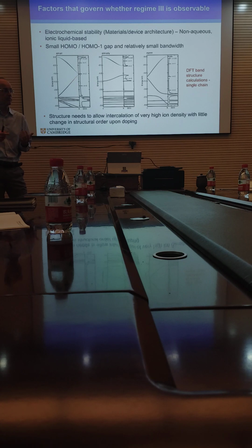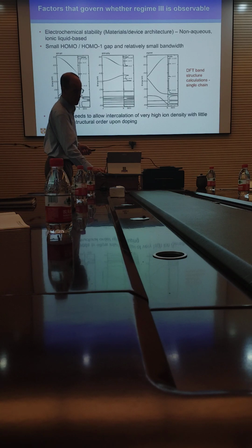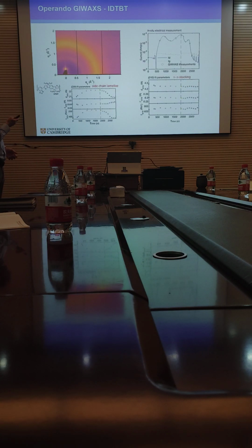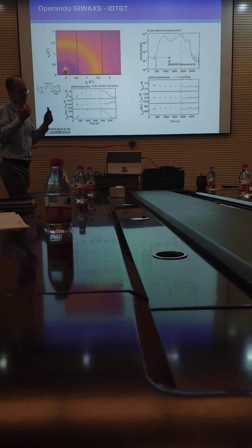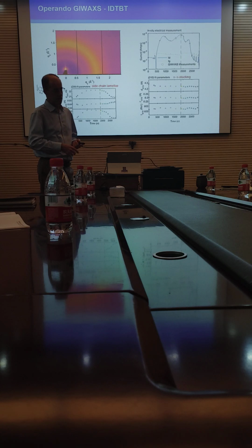IDTBT is quite a disordered polymer, and it's easy and possible to put more than one charge per repeat unit in here. You can see that here, this is an operando GIWAXS measurement where we actually charge and discharge the polymer and take the GIWAXS pattern. If you look carefully, you can see some variations in the GIWAXS pattern as we charge and discharge, but it's not changing very much. It's quite a disordered polymer, so you cannot see very sharp diffractions. But as you push these ions in and take them out again, the microstructure doesn't change very much. That's one of the reasons why we can put so many ions in without really degrading the microstructure. So that's essentially why it's possible to see this effect in IDTBT.